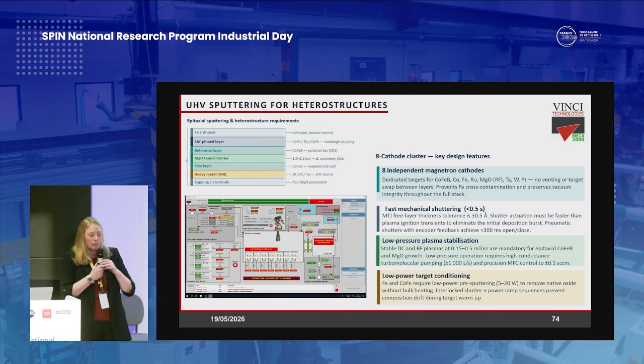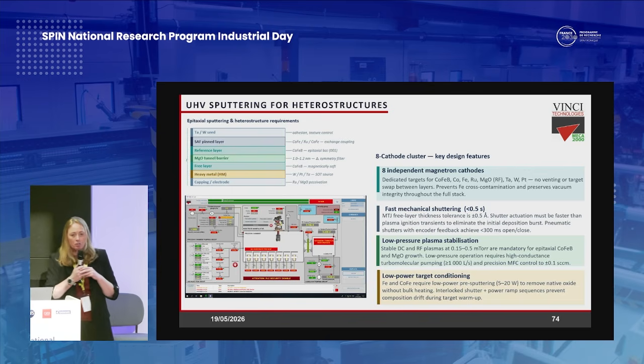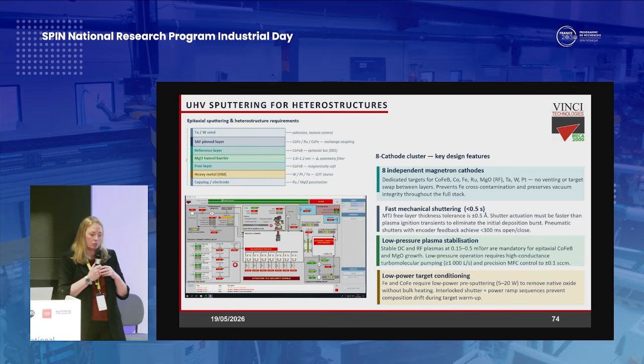So like I said, in these heterostructure systems, you're talking about combining several UHV magnetrons into the same system. It's very important to have fast shuttering, which can be done through pneumatic shutters with encoders, because once you have stabilized eventually the plasma at these low power, low pressures, you need to be opening and closing the shutters quite quickly to do AB structures.